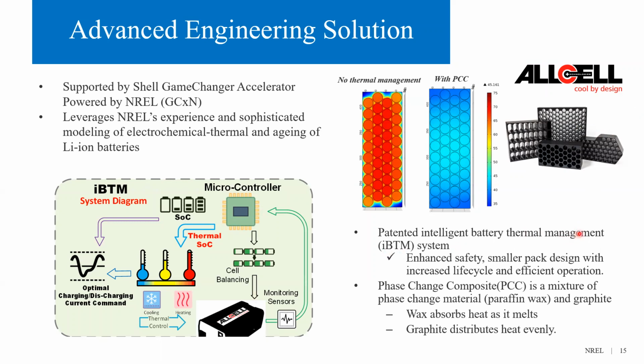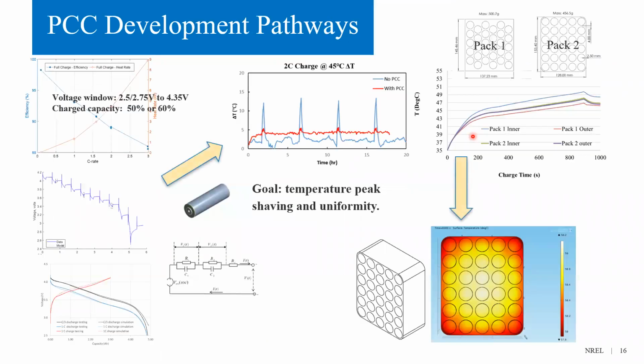AllCell's passive thermal management technology is based on the use of phase change composite, or PCC, a mixture of wax and a porous graphite matrix, to surround each lithium battery cell, absorbing and conducting heat away to extend the life of the cells and prevent fire or damage to the battery. A well-designed thermal management system is critical to battery performance and life.